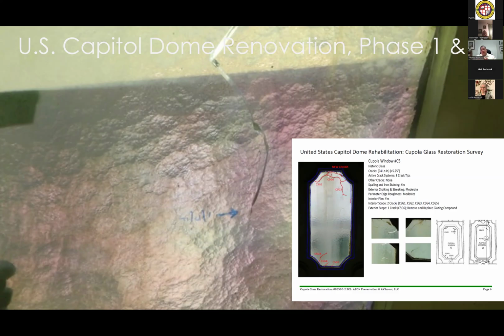So we communicated with the architect of the Capitol that these things were happening. These cracks, in fact, were for all intents and purposes alive, is how we would characterize it. And then we brought in senior research scientists from Corning Glass to talk to them about the nature of glass fracturing, the nature of their scoped out repair, which was to sort of wick through a very thin epoxy treatment like you might use for stained glass. So the guy that designed and developed that treatment was part of our team, and he said, no, you can't use that here. That's not what this is for. The glass fracturing guy said, no, the glass is going to continue to fracture. It's not stoppable. This isn't going to work.